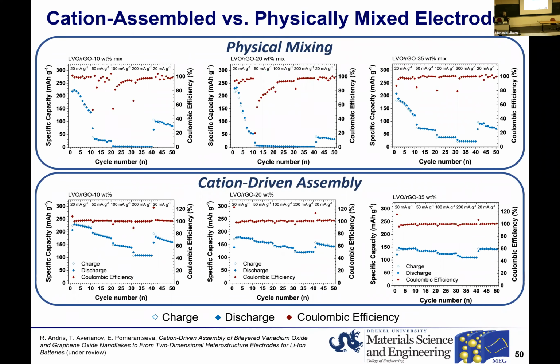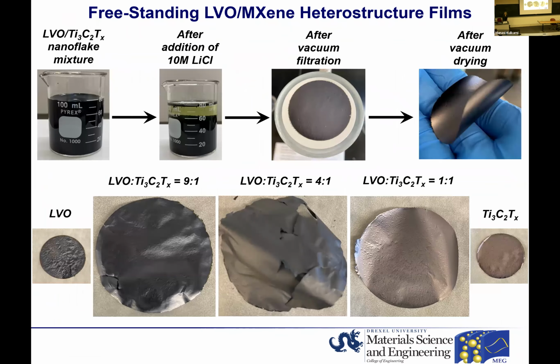And to prove that to you, I also show again the comparison with the electrodes that were obtained by physically mixing graphene oxide and bilayer vanadium oxide nanoflakes, and the difference is drastic. So see here the capacity drops to 0, while in this case we still have some capacity at the relatively high current density of 200 milliamps per gram. So I think this is a very exciting result that definitely needs to be developed further.